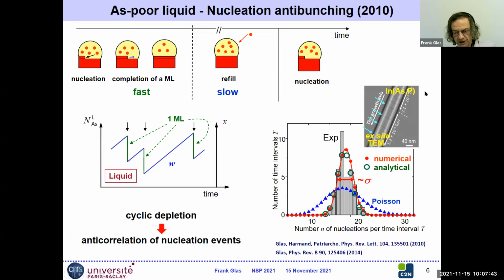Now, at this time, we did some experiments, and that was by TEM, but it was ex situ after growth. So during growth of the nanowire, we introduced marker layers of another material at equal time intervals. And then we could measure the length of nanowire grown between 2 of these markers. And we could then count the number of monolayers grown in successive equal intervals of time. And what we obtained was this gray histogram.